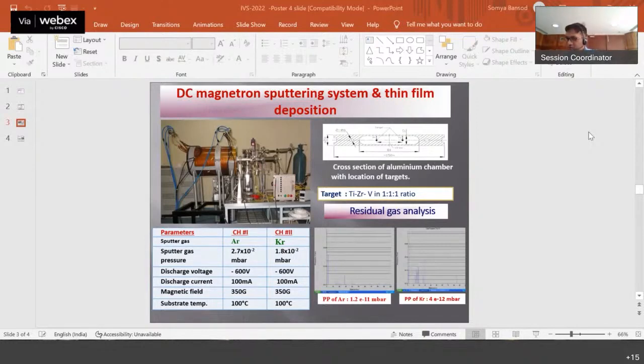Okay. Sorry, sir. Why are you using a DC magnetron? Actually, sir, the pole gap of the aluminium chamber cross section is very low, so the distance between the substrate and target is small. So we have to produce the discharge. We have to apply the magnetic field.